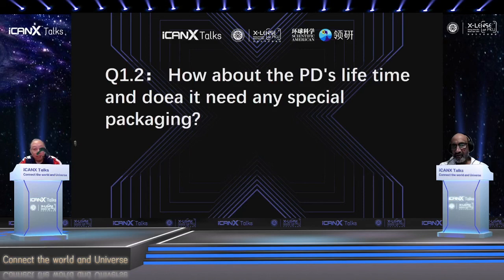Okay, and the next question is, how about the photodetector's lifetime, and does it need any special packaging? Okay, that's a good question. For the lifetime of the photodetectors, I think one thing is related to the materials. For example, the metal oxide materials are quite stable, and the electrode is metal, so the final device is quite stable. But for some other materials, for example sulfide, nitride or antimonide, these materials are not stable in air. So for these devices, we need some special packaging. Yeah, it depends on the material.